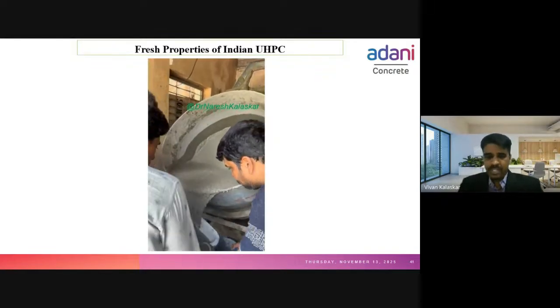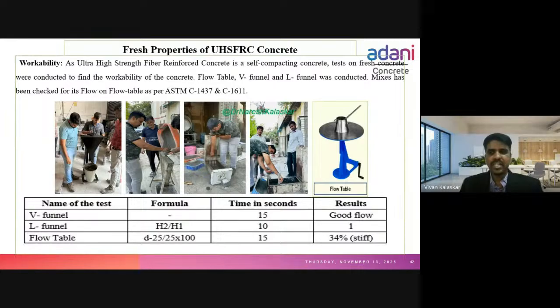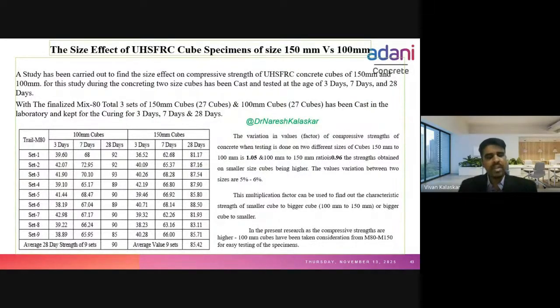So usually UHPC will be poured like this only. If we need any pumping requirement, we can change the admixture dosages, then we will get the required fresh properties of concrete. So these are a few fresh properties of concrete tests we have done. Workability test, V funnel test, L funnel test, flow table test. Flow was good, and L funnel result was 1, and it took 10 seconds, and the flow table was 15 seconds. These are a few fresh property tests as per ASTM C1437 and C1611.